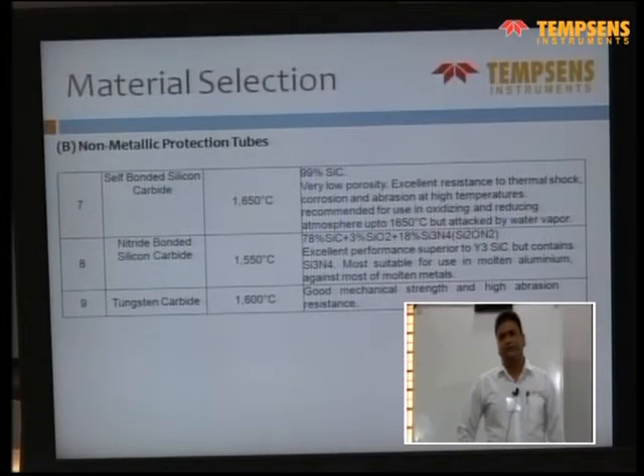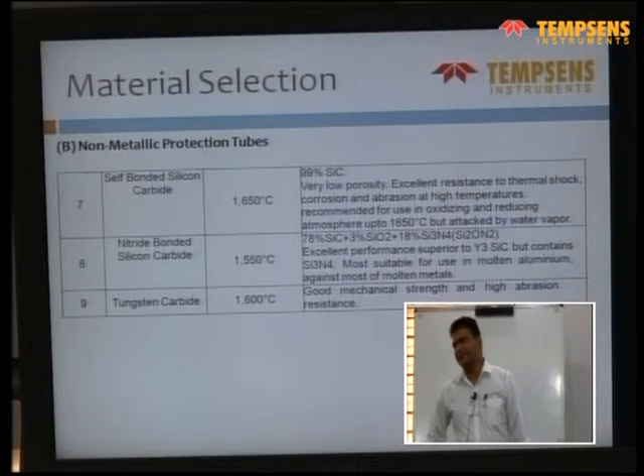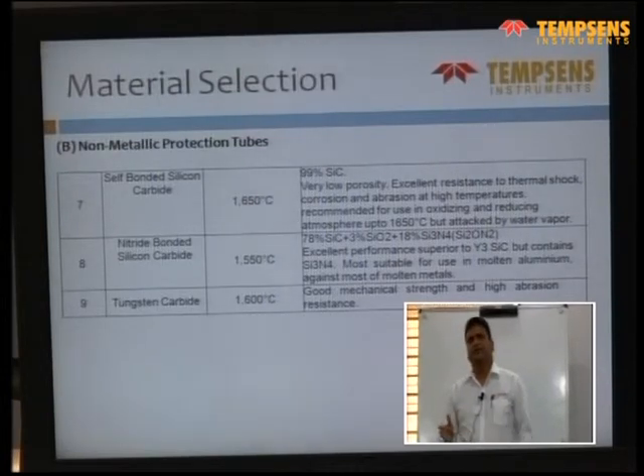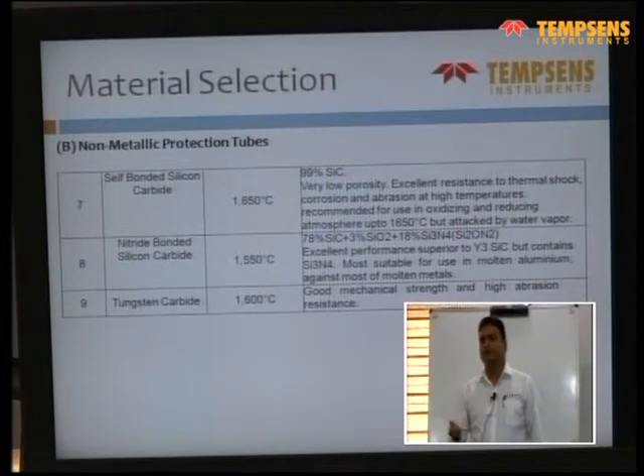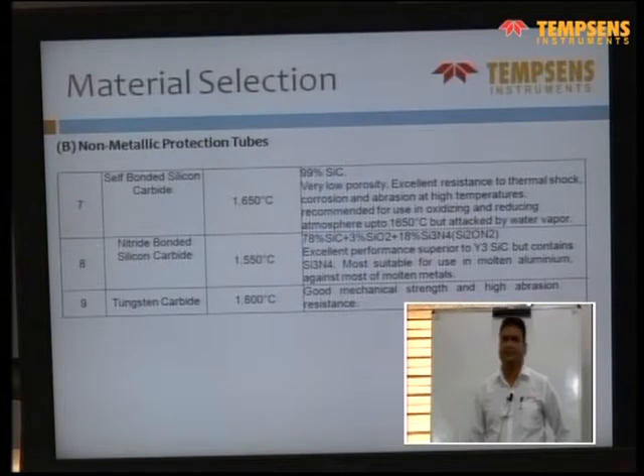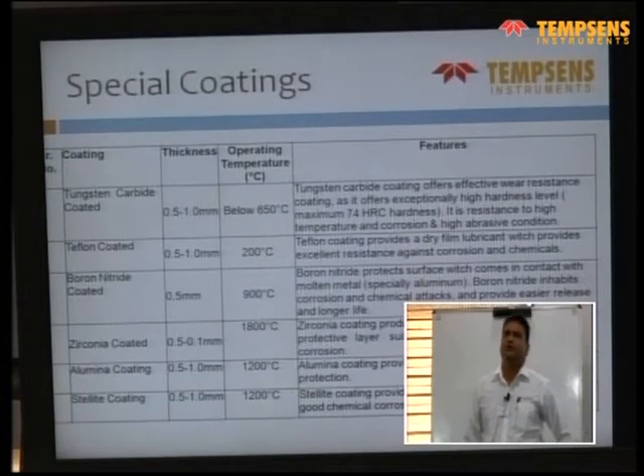So in case of a power plant, solid sintered tungsten carbide thermowells are used, which can give a good life in case of a coal mill application. The temperature is up to 300 degrees centigrade only in the coal mill application.